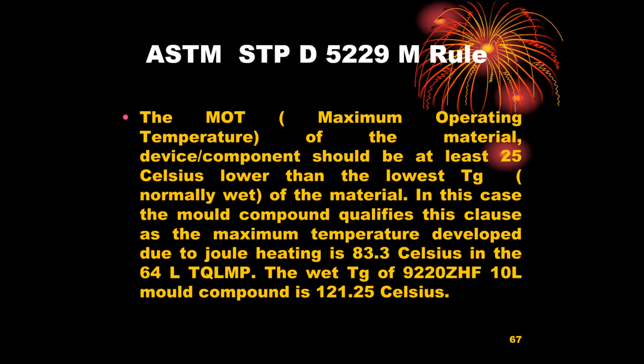Well, there is an interesting ASTM STP D 5229 rule. Coming to almost the end of my talk. I'm very happy that despite I started a bit late, I will be finishing within time. ASTM STP D 5229M has a rule. The maximum operating temperature of the material device component should be at least 25 degrees Celsius lower than the lowest TG, normally wet TG. Dry TGs are higher, and wet TGs are kind of lower for plastics after saturation equilibrium, at least of the material.